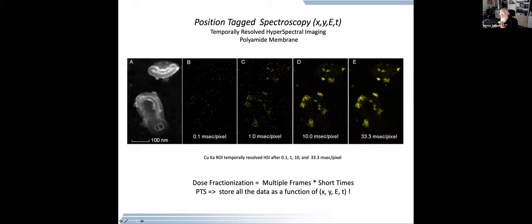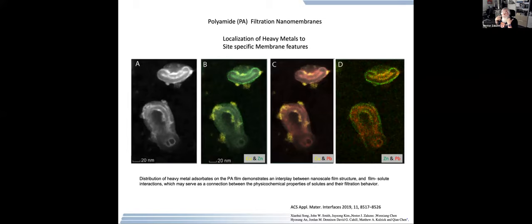The question is, is this structure representative of what was originally there? So here's the original image, and there's the microanalytical structure. I can look as a function of time for elemental species moving. I can tell that, yes, all of these features that we see here were present even at the very short time scans. So we're doing dose fractionation, just like you do in tomography. We do multiple frames over short periods of time, and we store all of the data as a function of X, Y, E being the energy of the spectra, and time. That means we can go to that polyamide membrane and map out very carefully and with confidence the heavy metal adsorbates on this polyamide film. We can see the interplay between the nanostructure of the film and the elemental species that segregate, in this case copper, zinc, and lead.